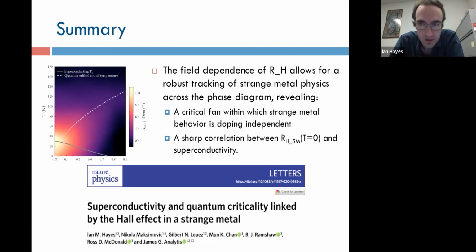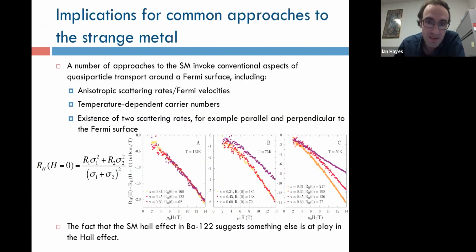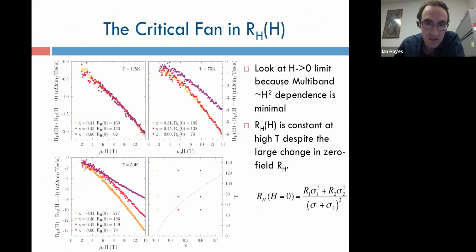I think generically you do expect whatever increase in RH you get from anisotropic scattering to decrease with field. So that way it is actually consistent. What I would like to see, and haven't seen, because I'm sure it's difficult in a system like this, is whether you can actually reproduce a consistent field dependence at high temperatures despite all these changing background conditions. It's probably not impossible. The question is whether you're just going to be tuning parameters at the end to make